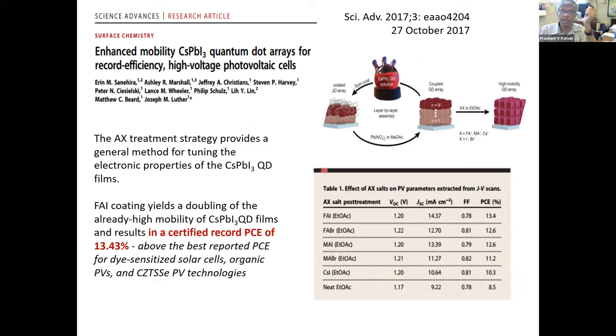One of the things is, when you make these colloids, there is a lot of ligands associated with it. Unless you remove these ligands by washing or annealing, you cannot make good contacts. And that is one of the things that is driving. And again, as I said, if the particle grows from 11 nanometers to 100 nanometers by annealing, we cannot still call it a quantum dot. It becomes like a bulk film. But in this case, they used a washing process to take away the ligands.